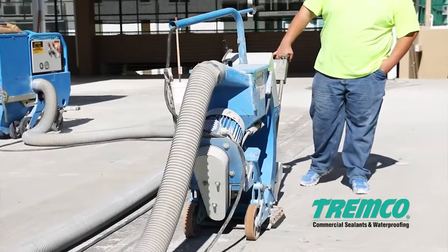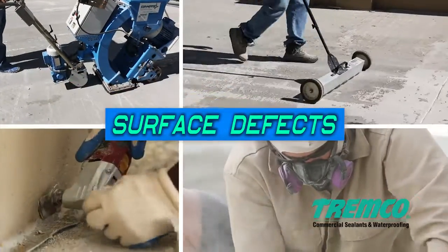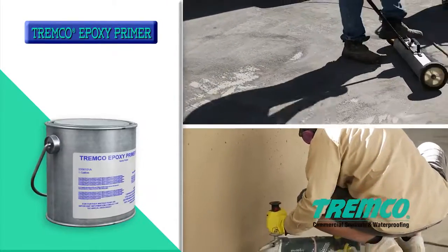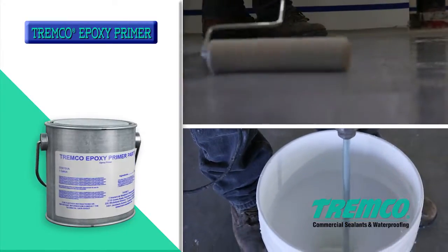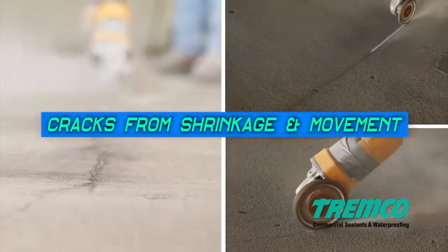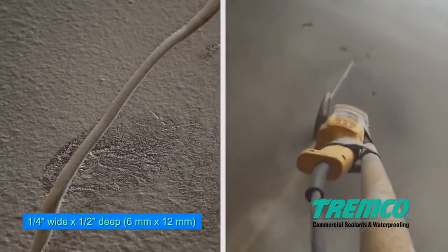Surfaces must be free of defects that may telegraph and show through the finished coating. Surfaces that are rough, such as fins, ridges, exposed aggregate, honeycombs, and deep broom finishes, must be leveled and made smooth by applying a coat of Tremco epoxy primer, sanded, or equivalent filler material. Shrinkage cracks that are 1/8 of an inch or 3 mm wide and structural cracks from building movement, regardless of width, should be ground out to a minimum 1/4 inch wide by 1/2 inch deep.